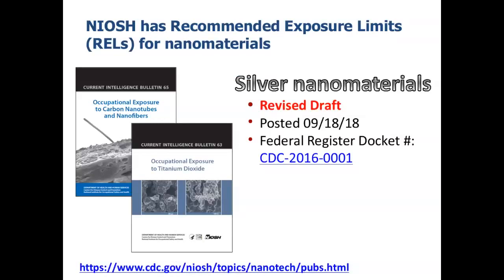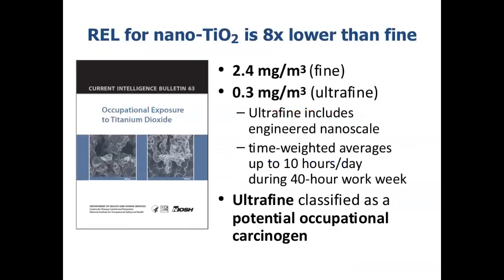One thing that was interesting with that was that based on new evidence acquired in recent years, the revised draft recommends an exposure limit more than 10 times lower for silver nanomaterials compared to total silver, which was different from the initial version that was posted. Similarly, the recommended exposure limit for nanoscale titanium dioxide is 8 times lower compared to fine titanium dioxide, as you can see from the values on the slide. So ultrafine titanium dioxide, TiO2, we'll refer to it that way as well. So the ultrafine TiO2 includes engineered nanoscale titanium dioxide and was also classified as a potential occupational carcinogen.